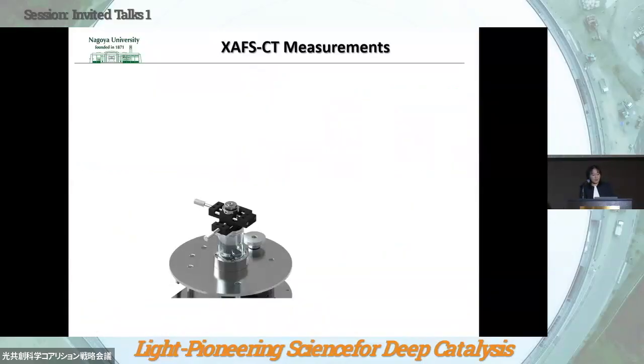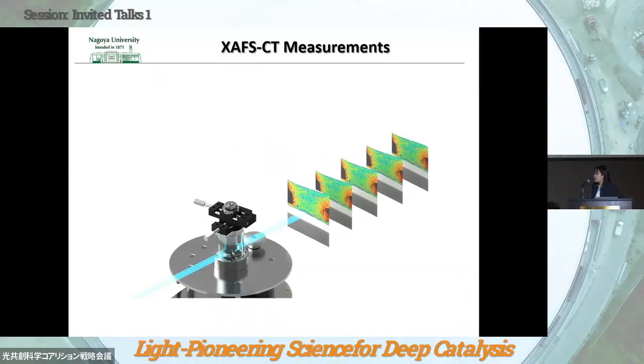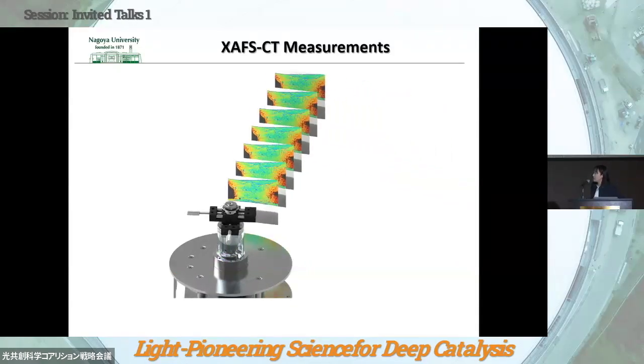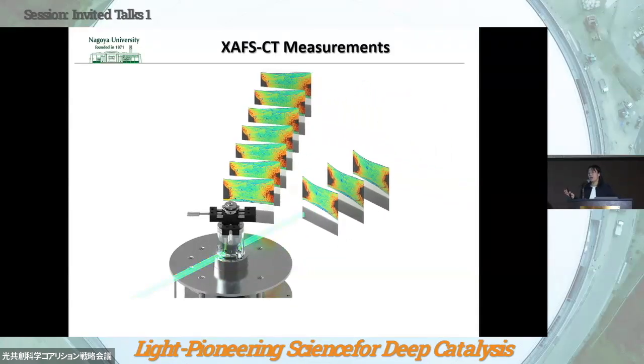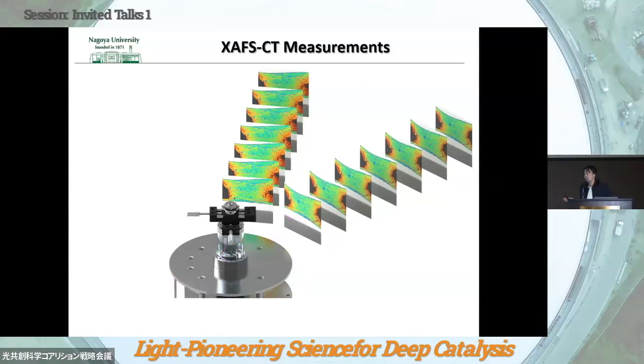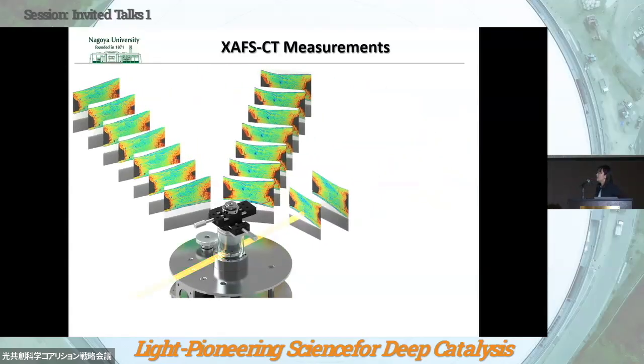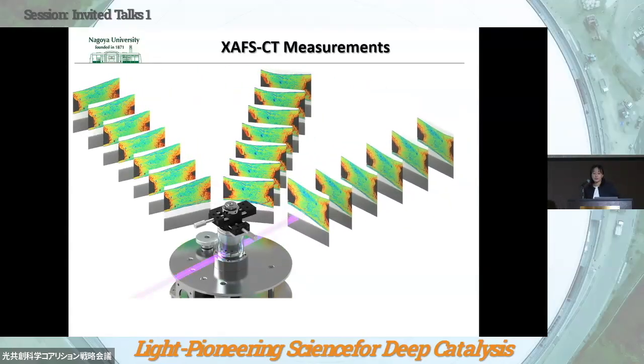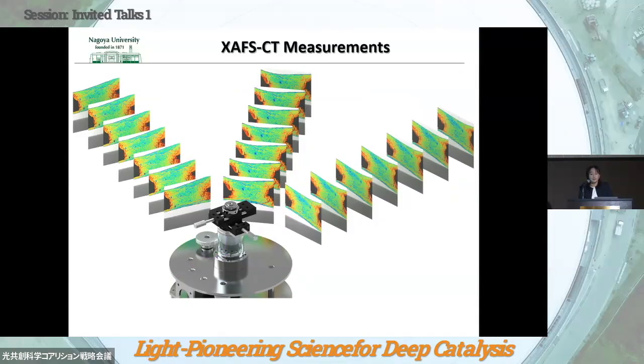So I would like to show you the scheme of the CT measurement. We changed the X-ray energy and recorded the two-dimensional data, and then changed the angle to the incident X-ray by rotating the sample, and we repeated the measurement again. So after the beam time, we end up with a sea of imaging data.